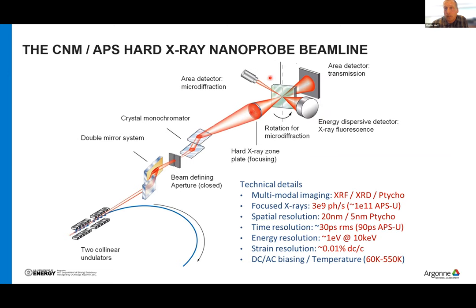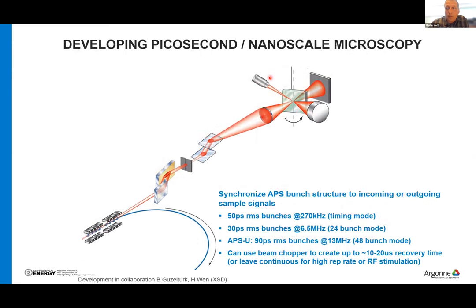And so we're able to then look at the physical truncations and also the structural perturbations inside of the object. So we can develop the time resolved variance of that by relying on the pulsed nature of the source. And this is gathering these bunches into what is currently about 30 picosecond RMS bunches, and that will of course go up to about 90 picoseconds under the upgrade. But that gives you effectively a pulsed source of X-rays. And you can build your entire experiment at a fixed time slice relative to a dynamic process.